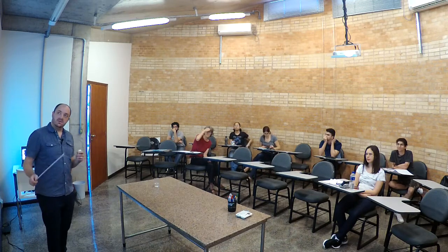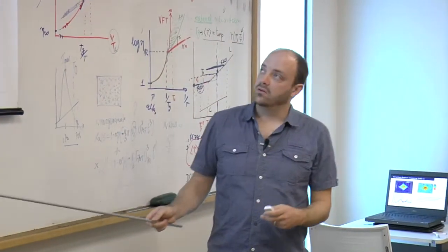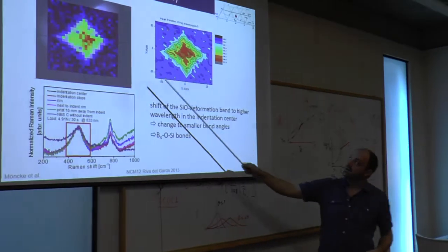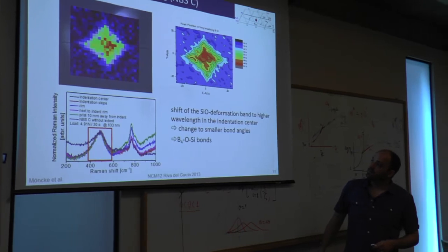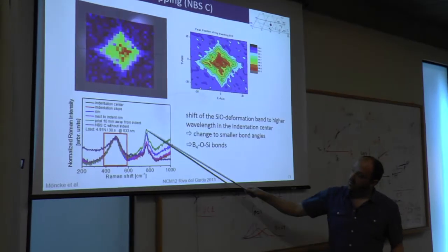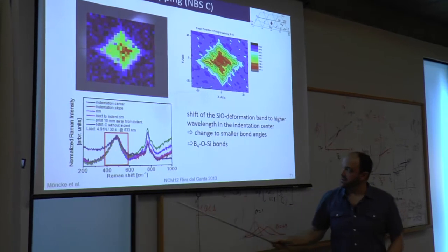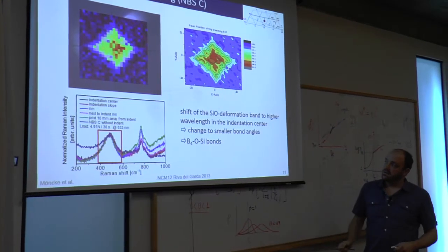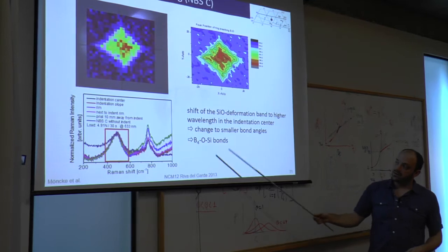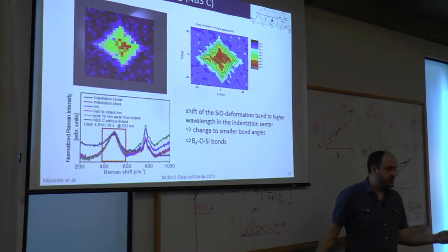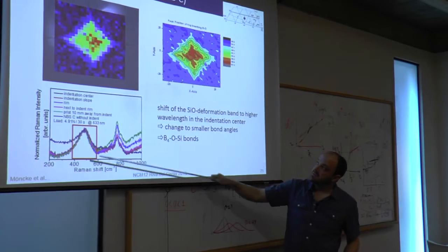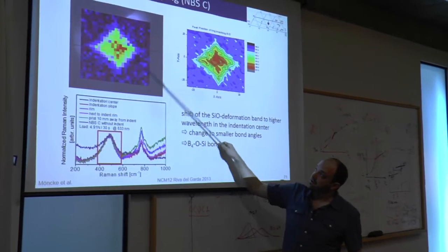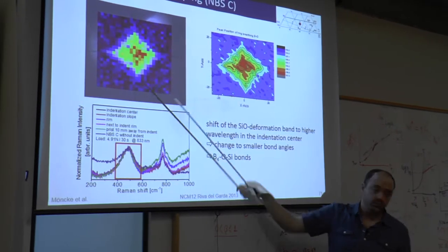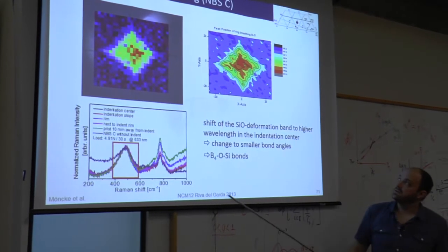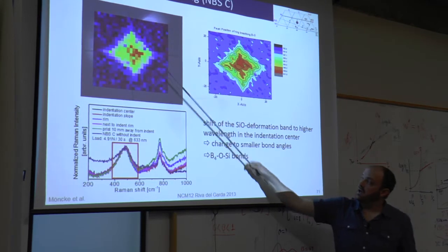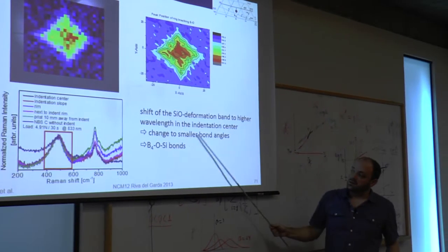Yeah. This is something else you can do. This is a mechanical example where they've indented the sodium borosilicate glass. And you can actually pick one of these bands. So if you know your indenter, for instance, shifts the intertetrahedral angle to smaller angles, you're going to see a shift in the band. So if you pick the position of one of these bands, you can measure things like the intertetrahedral angle.